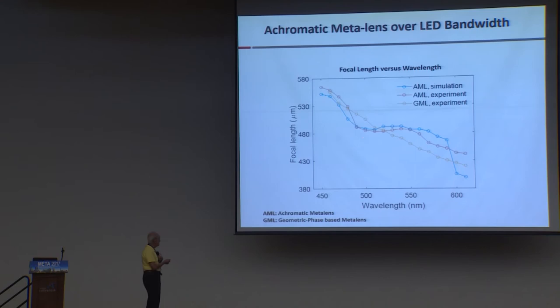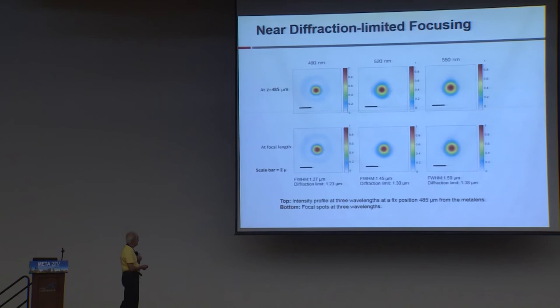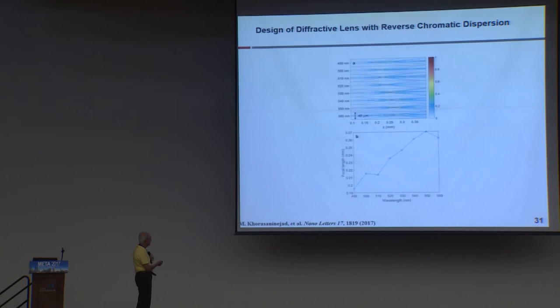It goes from the old work of Robert Wood in the early 1900s, the Wood anomalies and so forth. But basically, if we satisfy this condition that the unit cell is less than the wavelength in air and the wavelength in the titanium oxide pillar, we can have coupling, we can have guided wave resonance, and this expands the phase coverage. So the net results of our experiments are here. We have achieved basically constant focal length across 60 nanometer bandwidth, which is already significant. Simulation experiment go along pretty well. This is just the reference structure done with the Berry phase lens. And so forth, we can get very nicely close to diffraction limit at the three different wavelengths here at the two edges of the band and in the center.